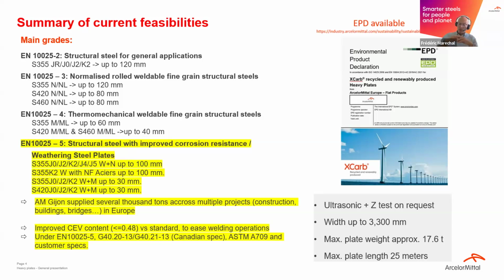This means, in short, that the carbon equivalent will be improved in thermomechanical. So this has a positive effect on the aptitude to welding. And then, and this is, of course, important for our today information webinar, we also produce plates, heavy plates, in weathering steel, so with improved corrosion resistance. And here you can also find the so-called popular classical grades like S355J2+N, for instance, W, this means weathering. So this we roll up to thicknesses of 100 millimeter thick.